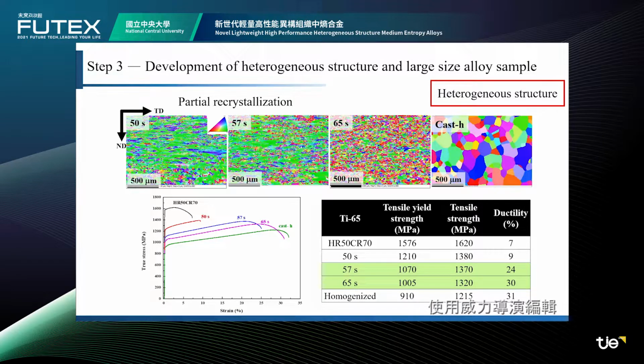Moreover, we explored the mechanical properties under partial recrystallization. The strength of titanium 65 at 57 seconds and 65 seconds is increased by 100 to 200 megapascal compared to homogenization, while the ductility does not reduce too much at the same time. By EBSD figures, it can be seen that the alloy is composed of retained deformation grains and fine recrystallized grains simultaneously. This structure is also called a heterogeneous structure, which is the most popular subject in alloy research recently.